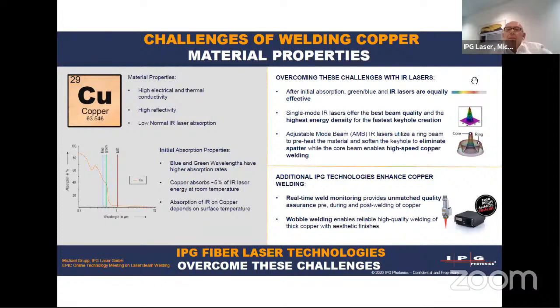Another technology we meanwhile have is the so-called AMB technology, adjustable mode beams, which means a double laser with a laser in the core of the fiber and a ring around this core. This is available with different ratios and diameters, say 50 micron core with 150 micron ring, or 100 micron core with 300 micron ring. These lasers are utilized to optimize processes. We get a preheating of the material by the ring and a softening of the keyhole, and in this way we can eliminate spatter, for example, and enable really high-speed copper welding processes.